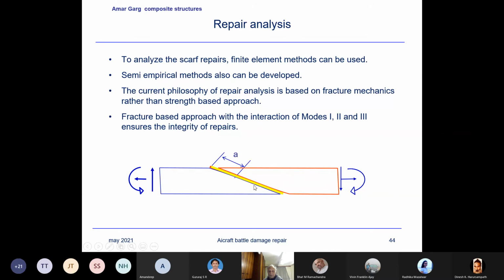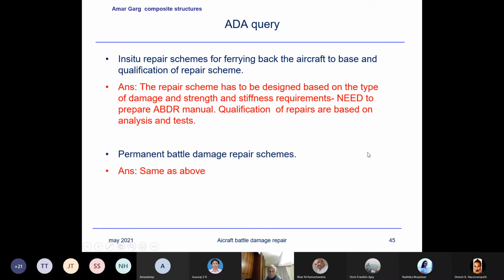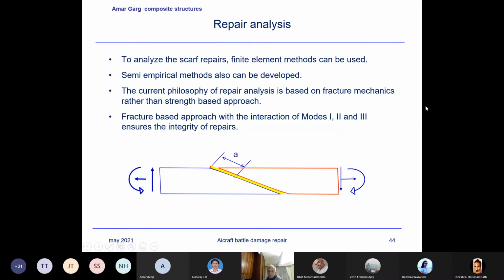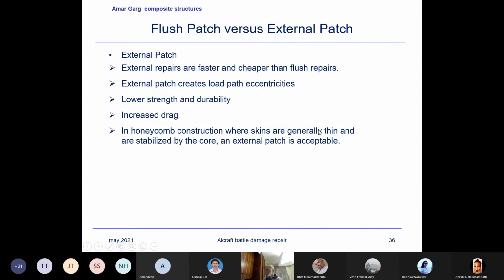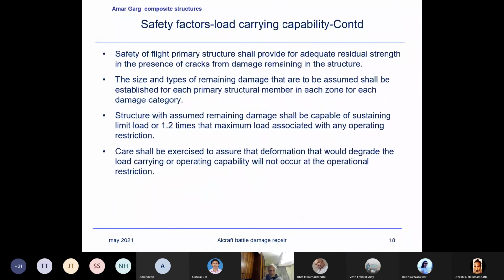This is just showing a coupon, which normally we consider in order to justify the repair. I've done a lot of work, in fact, on the repair justification. So we would consider fracture mechanics approach rather than the conventional strength approach. Like I talked about the bond line fracture mechanics approach, and I'm very conversant about that. I developed this methodology, in fact, for the fracture mechanics analysis some time back. Okay, now I can't go into the details because it's again a big subject for the repairs of these structures.